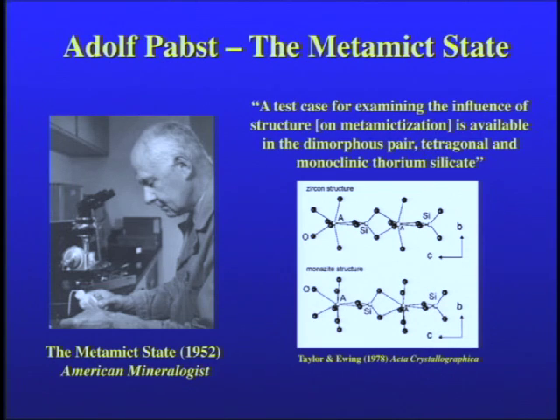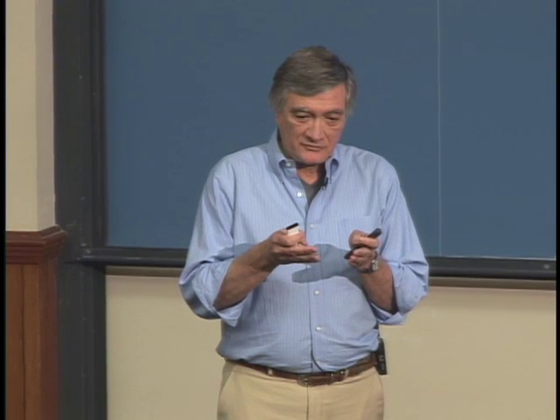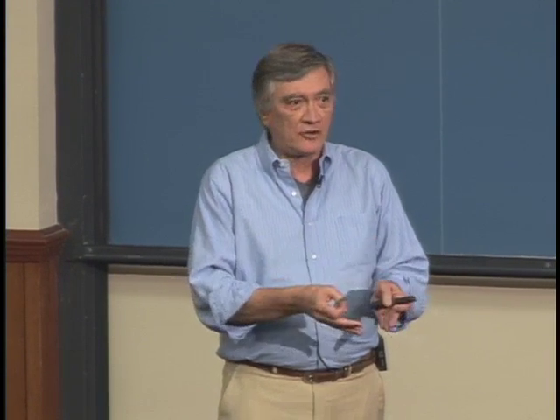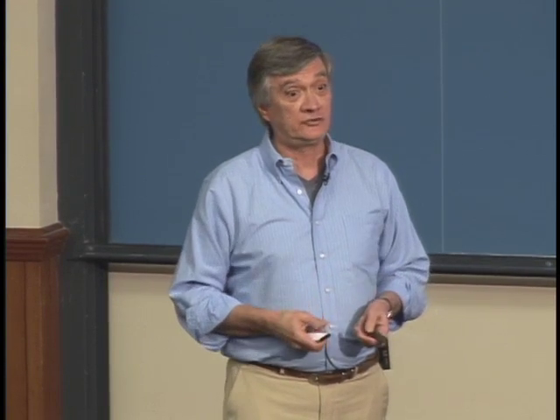In his paper, though, he discusses thorium silicate, ThSiO4. It has two polymorphs. Huttonite, Colin Hutton was my advisor, and a professor here, so that kind of caught my eye. And huttonite is isostructural with monazite, an important mineral for geoscientists. And then thorite, the tetragonal polymorph, is isostructural with zircon. And Hutton made the observation, well, the huttonite's always crystalline, the thorite's always partially metamict. There seems to be a structural control.